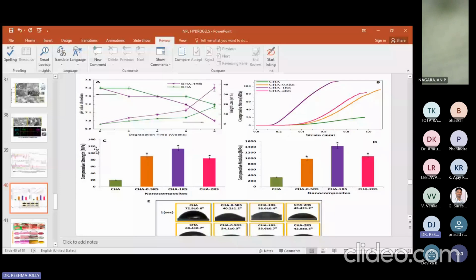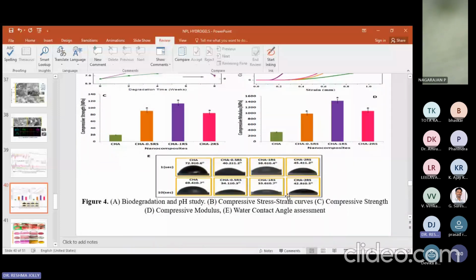Then we performed the water contact angle assessment also, because hydrophilicity plays a very important role if we are talking of a biomaterial. For that purpose, we took images after a second and after 10 seconds, and we found that the material is quite hydrophilic. As you can see, the angle for the binary system is 72, and after 10 seconds the ternary system changes to 33.6 degrees. So the ternary system is more hydrophilic, which is a good perspective to consider.